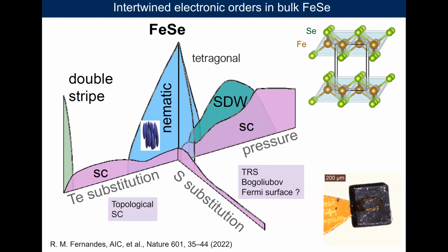For example, topological superconductivity has been proposed to exist at about 50-50 substitution of selenium and tellurium, somewhere on the top of the dome here. That would be topological superconductivity, where you have topological surface states but the bulk is still a normal superconductor. So this is an ideal setting for a system. And another proposition made recently is that these materials could also harbor unusual time reversal symmetry breaking, and potentially there could be a system where we could look for Bogoliubov Fermi surfaces in the tetragonal phases.